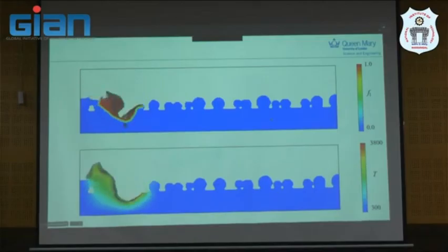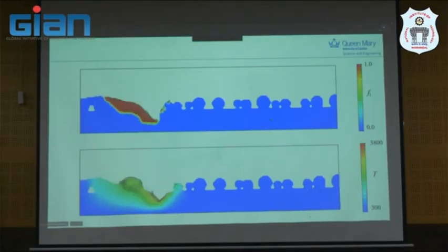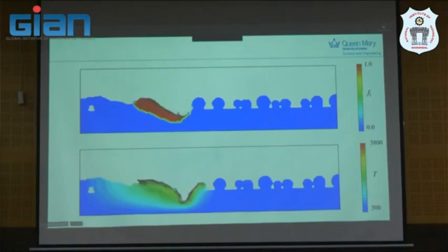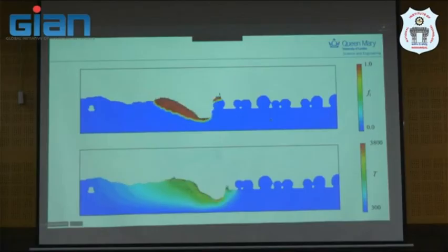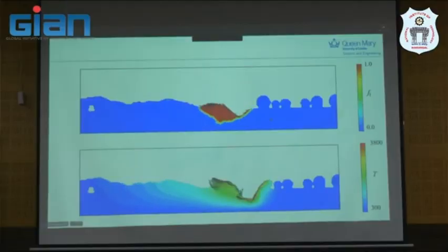Due to the extremely high laser energy density, here, a distinct concave shape is forming in this area. If the laser energy is large enough, the keyhole will form, I think.